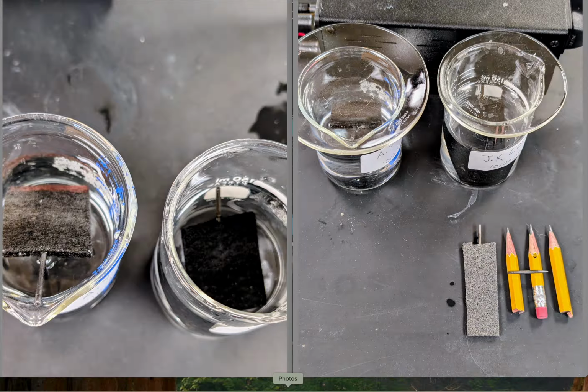Now look carefully at the one on the left, the first beaker on the left, and what looks like some deposit on the cathode. We use the DC power supply, and that is presumably mixed species of manganese +2 and manganese +3 oxides. Now we'll confirm that with scanning electron microscope and micro XRF, and we should be able to get some information on that. It's serving as not a scavenger electrode, but simply a cathode where hydrogen is being produced.